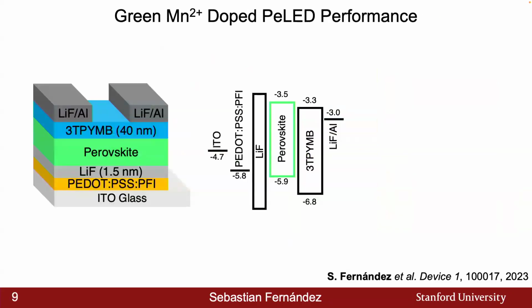So to skip a lot of the really hard work that went into optimizing the device up to here, I'll briefly highlight just 2 key differences from the 2019 device. The first one is including this insulating 1.5 nanometer lithium fluoride underlayer. And the reason for this is twofold.